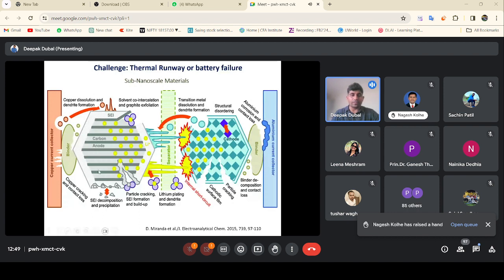So what happened in the batteries? You can see here we have carbon as an anode material and lithium intercalated metal oxide as a cathode material. When we charge it, these lithium ions, the yellow balls, move and go into the carbon material. But the problem is that the intercalation potential and the deposition potential of lithium onto the graphite are very close. Both these potentials are really very close to each other.